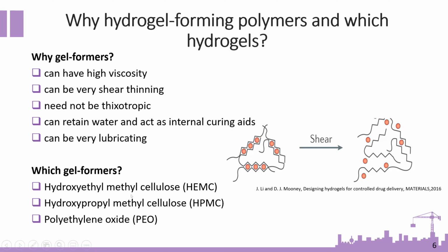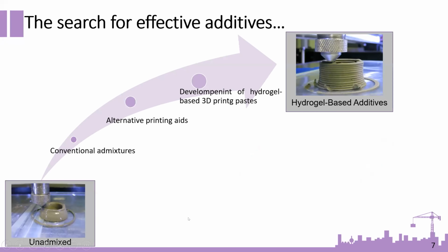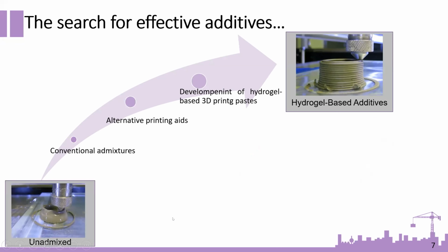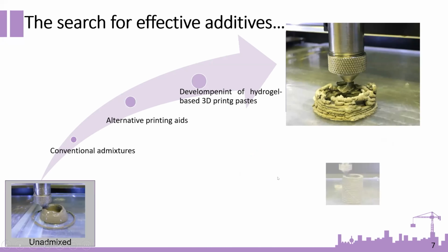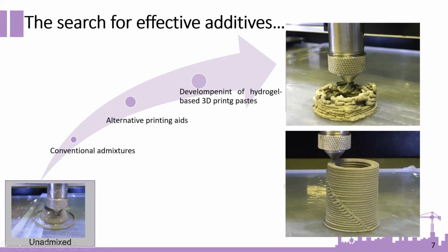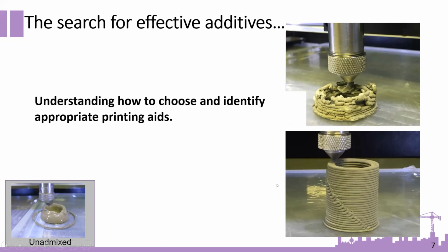Therefore, after screening a number of candidates, we selected three hydrogel forming polymers that were also stable under shearing and stable under the high pH of cementitious materials. These hydrogels were hydroxyethyl methyl cellulose, hydroxypropyl methyl cellulose, and polyethylene oxide. So here you can see the pathway that I used in order to select hydrogel forming polymers. But even among the hydrogel forming polymers, our results showed that not all of them give us good printability outcomes. So our work is based on understanding how to choose and identify appropriate printing aids.